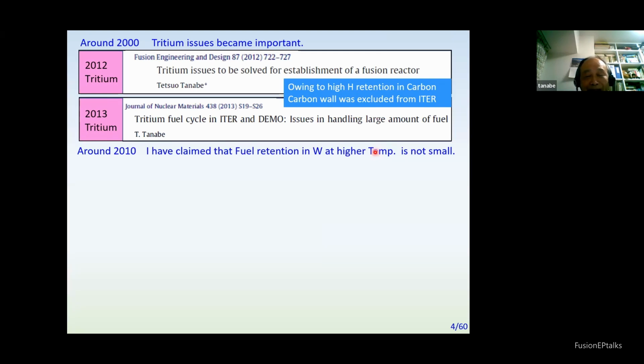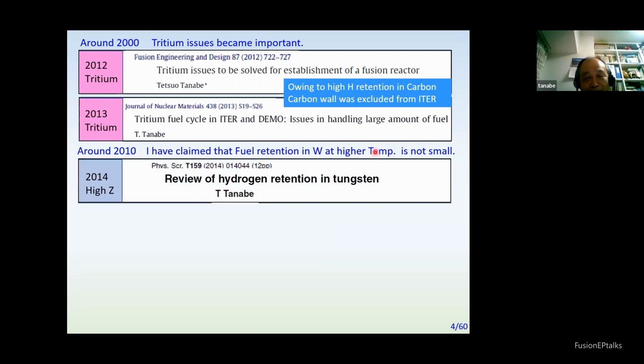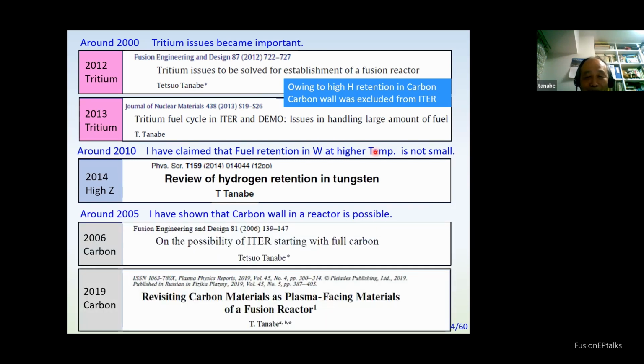But as I told you, for fusion reactors high Z material might not be the best one. So we have to do research on other candidates. In some sense, a comparison of high Z and carbon low Z materials is necessary. So I tried to study hydrogen retention in tungsten, and I found that hydrogen retention in tungsten might not be small. So carbon could be, in this respect, the starting material. So at the moment, my position is to use carbon as plasma facing material in the reactor.